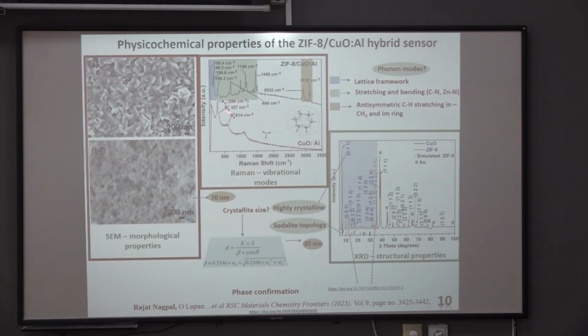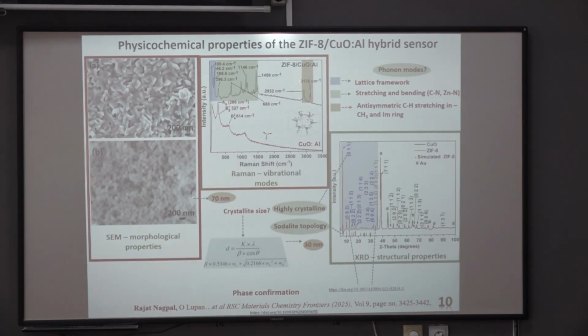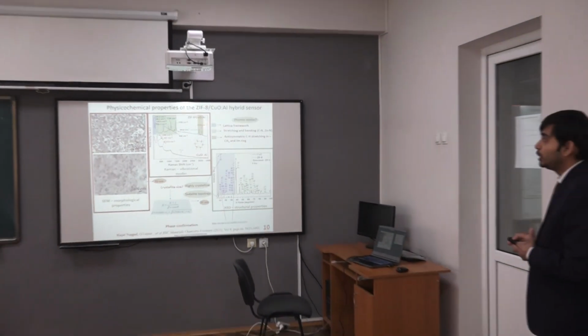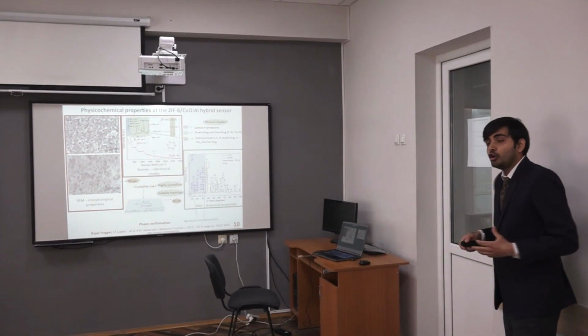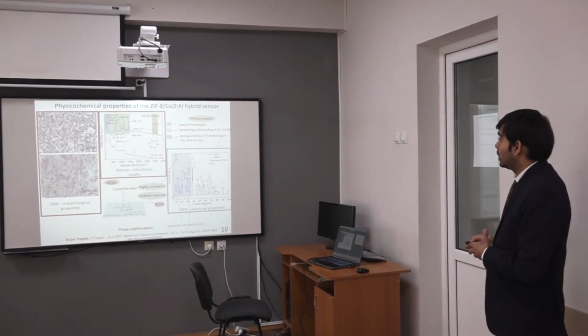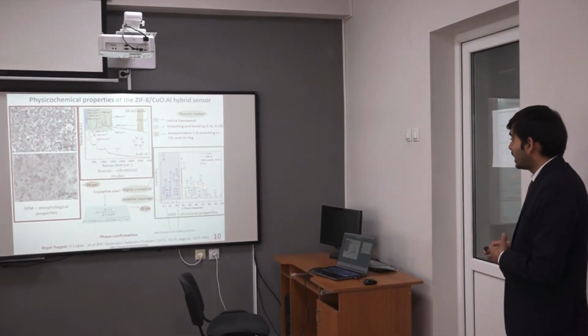In the Raman spectra, it provides vibrational mode contributions. Here we can see it has been classified in 3 regions. Starting with the blue region, it corresponds to lattice framework based vibrations. The green region corresponds to stretching and bending vibrations, followed by, at high wave numbers, antisymmetric stretching vibrations in the imidazolate ring. Now, to get structural features, here we can see the XRD pattern.